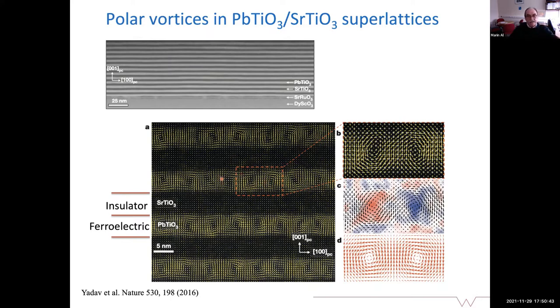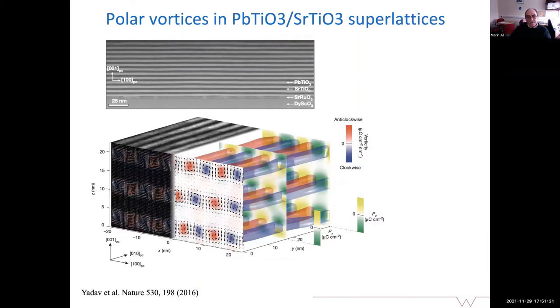So mostly in this superlattice, when you have a ferroelectric layer of very finite thickness between two dielectric layers like strontium titanate, so lead titanate, strontium titanate multilayers. And if you do scanning transmission electron microscopy, you are able to map this polarization, and then surprisingly, this polarization generates these vortices, which are chiral, and always you have pairs of positive and negative chirality. And they are practically like tubes, if you want, resembling pretty much the skyrmionic phase in ferromagnets. But this is along the ferroelectric layer in this way.